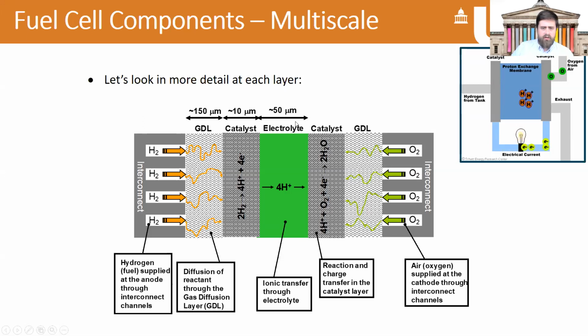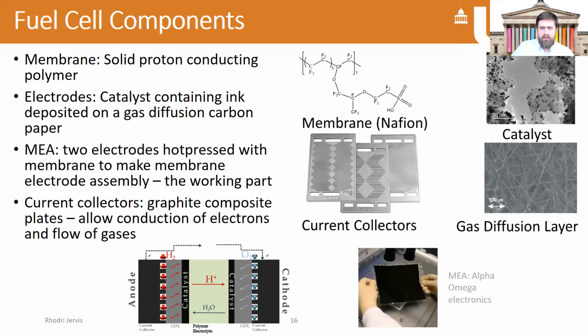Then we have this polymer electrolyte, which is based on Teflon, actually, on non-stick PTFE backbone, but it has special side chain molecules that allow the transport of these charged protons through the electrolyte, and that's quite a thin layer, again, probably 50 micrometers, maybe a bit less in modern membranes, and there's quite a lot of polymer science and chemistry that goes into that material. And then you have the same sort of thing mirrored on the other side of the fuel cell, where the oxygen is delivered through the same materials. Often these catalysts are quite similar, based on platinum metals. I'll come on to that in a second. So as I say, there's many components that need to come together to make a fuel cell work. These are some of the main ones. So I've mentioned this membrane, which is actually acting as our electrolyte.